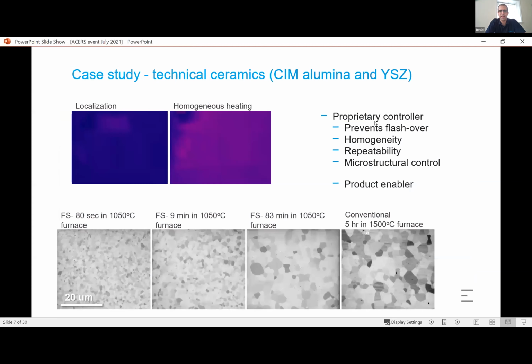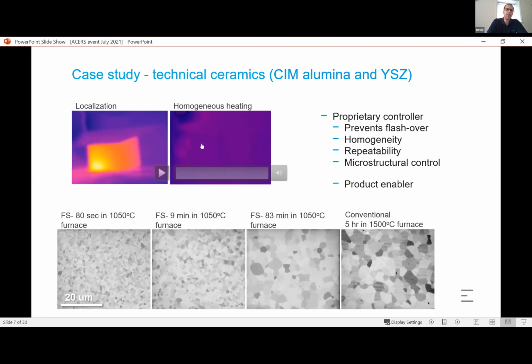Okay, so just come back to the fundamental zirconia example. I'll show you this is a cylinder of zirconia sandwiched between two electrodes. You're seeing a non-linear shrinkage there. That's some optimized flash settings, but without the use of the controller. Then if we switch the controller on and it's doing its thing, we start to see a much more uniform shrinkage across a bulk piece of ceramic.